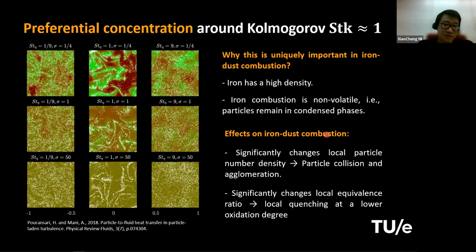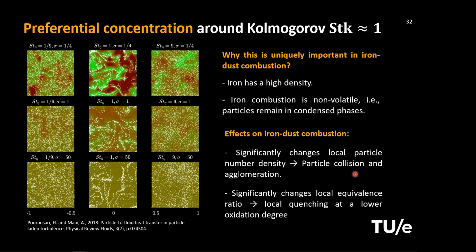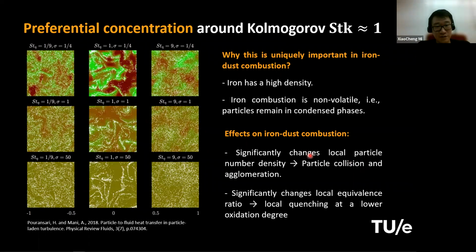And what could be the effects of preferential concentration on iron dust combustion? One thing is that this can significantly change the local particle number density. So particles can collide in these very narrow and highly concentrated regions, although the overall average volume fraction of iron is still quite low. In typical applications, it's below 10 to the -4, right? It is actually very low, but if you have this preferential concentration in some regions, the particles can collide and then form agglomerations. And then the second one is you can change the local equivalence ratio. So maybe in a certain region, where the particles are highly concentrated, you can have either local quenching or not complete oxidation up to Fe3O4, right?